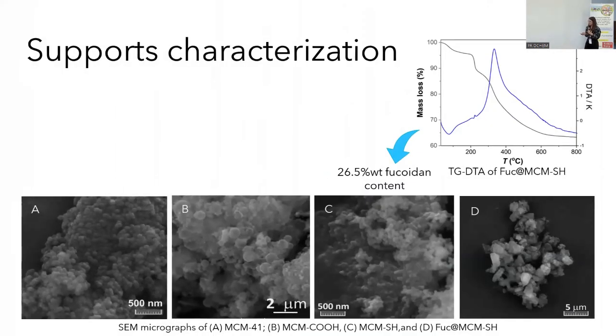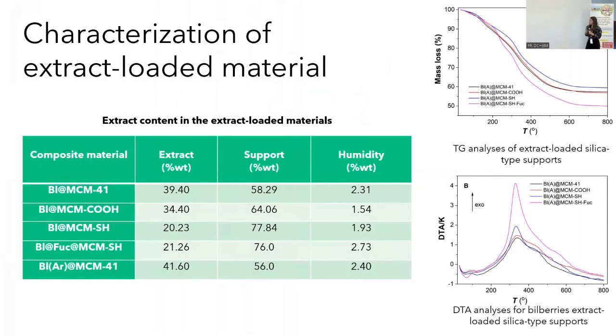The SEM investigations revealed that all the samples possess spherical particles with diameters lower than 100 nanometers. You can see that the fucoidan-coated particles tended to form agglomerates. The extracts were loaded on the silica matrix using the impregnation method, followed by solvent evaporation in high vacuum. The extract contents were determined using thermogravimetric analysis, and due to the high porosity of the materials, high contents of polyphenolic extracts could be encapsulated, up to 39%, as you can see.